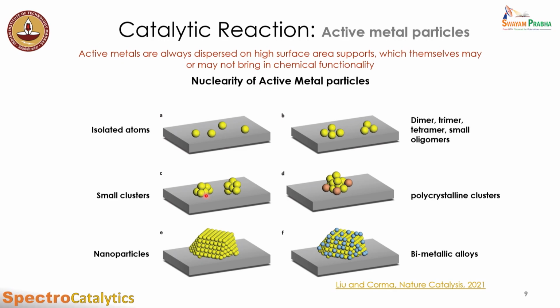If we further increase the loading, we can have polycrystalline clusters. That means now the crystal size is big enough, or the cluster has a high enough number of active metal particles, such that we can form different ending geometries. It can be a 110 plane, 111 plane, or 100 plane, and depending on this ending geometry, we have a different atomic configuration of these atoms on the surface that is exposed to the reactive atmosphere, and they can perform differently.